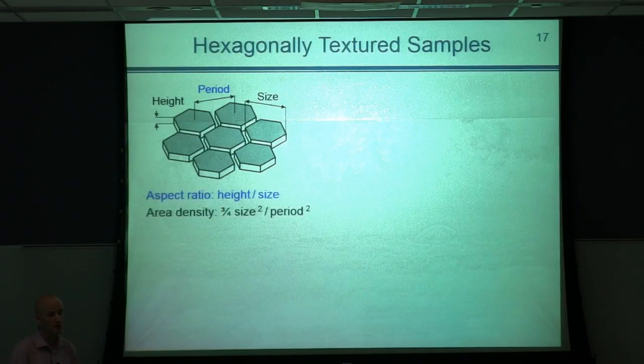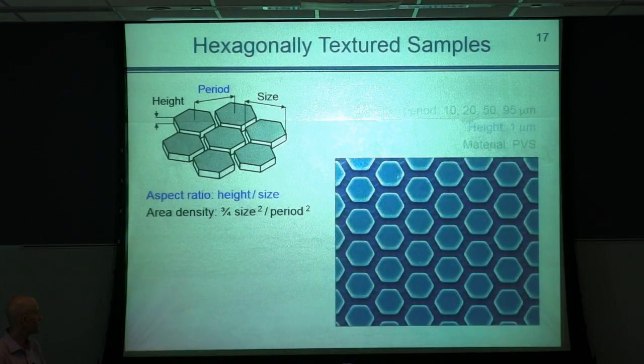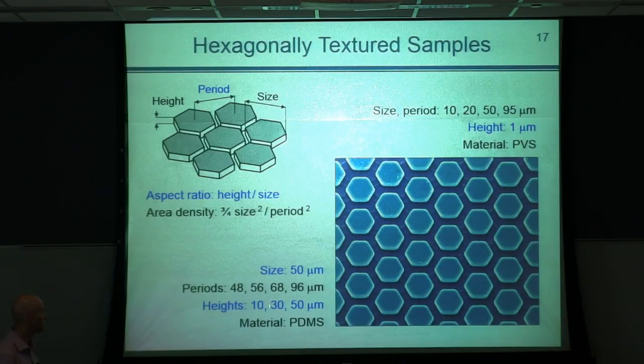So in order to test both hypotheses, we had to create these structures. And this is a schematic representation of hexagonally shaped projections that we cast from different materials. We worked with polyvinyl siloxane and PDMS. This is a schematic with 3 parameters that are important: height, period, and size. And this is the same image that shows PDMS structures, and we cast them to have different aspect ratios, area densities, height, size, and period. So we ranged all parameters in order to see how they operate.